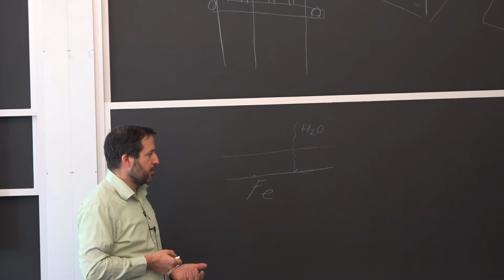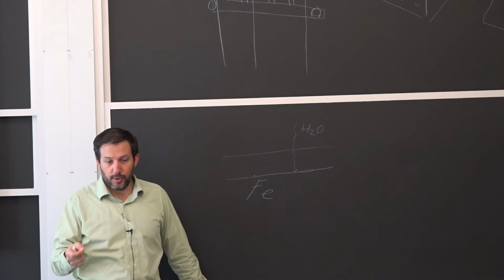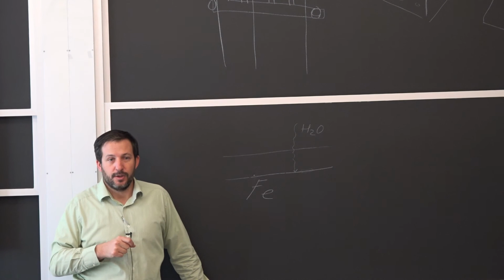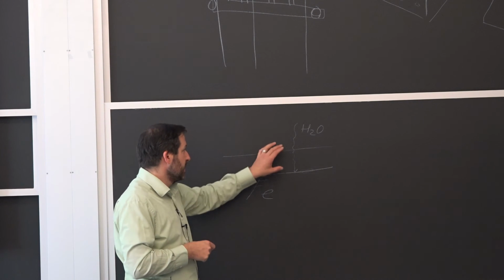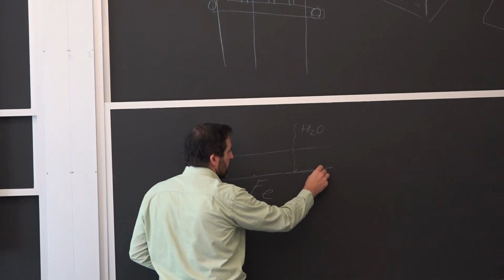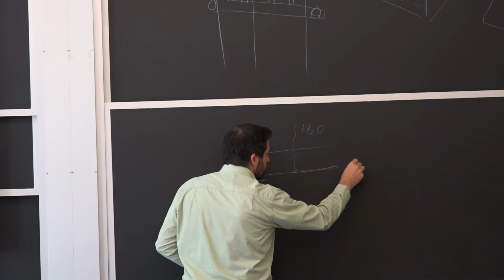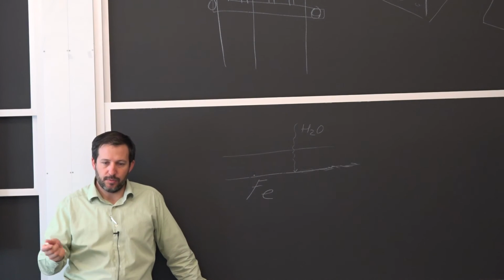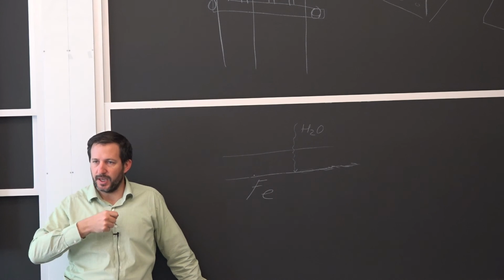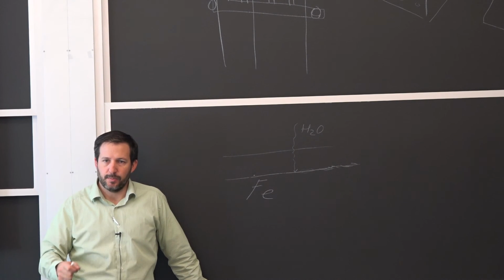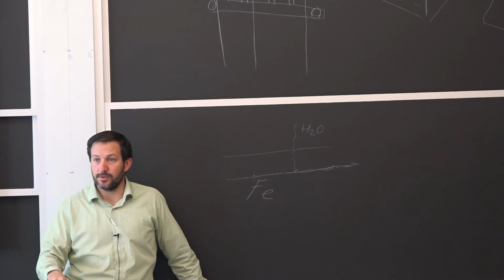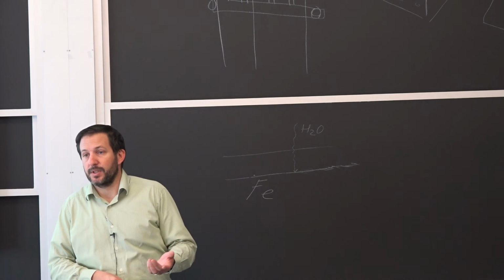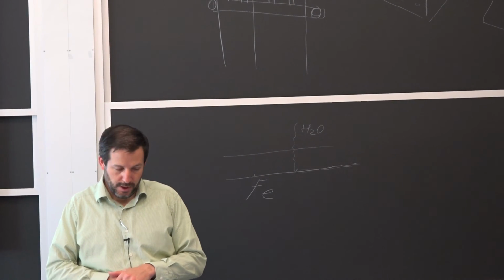So if you want to say, I'm going to put a coating on this and it's not going to corrode in, say, 15 years in water, you're looking at those specialized hard coatings that are going to require you to put your roughness in the first place to get a mechanical adhesion with the steel at the same time. So you have to do a little bit like you do with the hot dip galvanizing. You sandblast the surface, make sure it's dry, then you put your coating on, you let it dry long enough, and then you're looking into your long-term life. So it's used for ships, for example, or any very special structures.